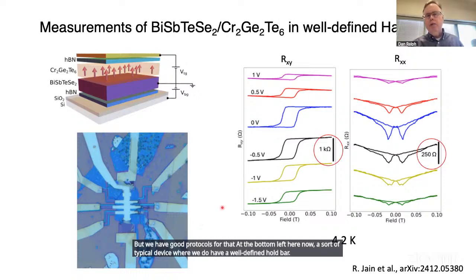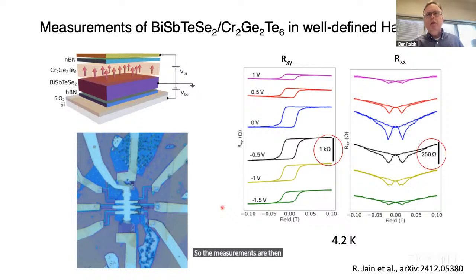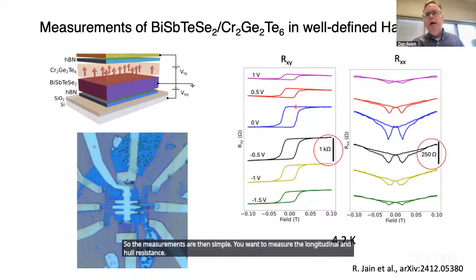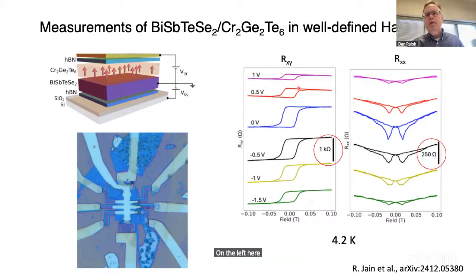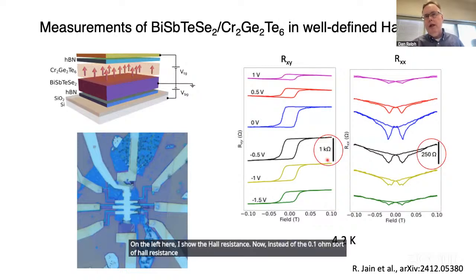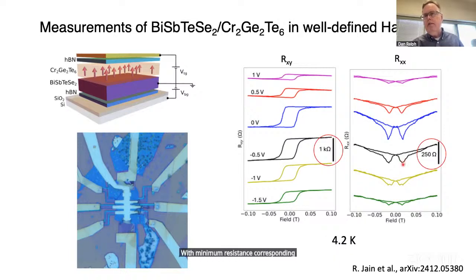So the measurements are then simple. You want to measure the longitudinal and Hall resistance. On the left here, I show the Hall resistance. Now, instead of a 0.1 ohm sort of Hall resistance, the typical scale is about 1 kilo-ohm. And we also see very nice butterfly characteristics on the longitudinal resistance, with minimum resistance corresponding to topological edge states along magnetic domain walls as the magnets undergo reversal.